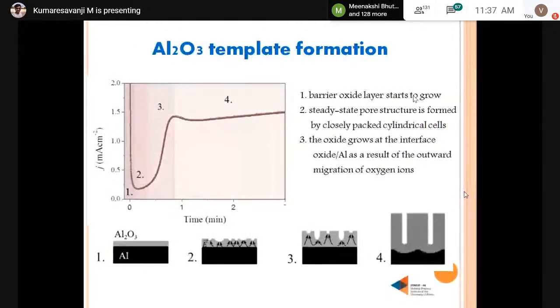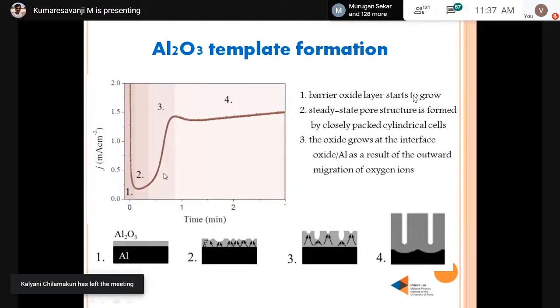When you start the anodization, in the first process the aluminum oxide will form. That is what we call the barrier layer. Once the barrier layer forms, in the second step a steady state pore structure is formed by closely packed cylindrical cells. Then the oxide grows at the interface of oxide and aluminum as a result of the outward migration of oxygen ions. Once we increase the time of anodization, the pore length will increase. So we can easily tune the nanopore diameter and pore length just by controlling the anodization conditions.